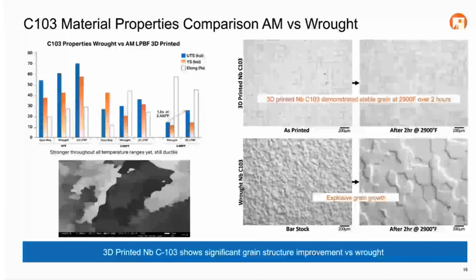And so we get a refined microstructure, so we're going to get Hall-Petch strengthening as well as this dispersoid strengthening effect that we wouldn't typically expect to see in the wrought counterpart. And so why is that important? Why do we see higher temperature strength and better creep performance? That really comes down to those secondary phases. And so you can see here, when we look at the as-printed material versus the bar stock material, you kind of see the difference in this weld macrostructure view.